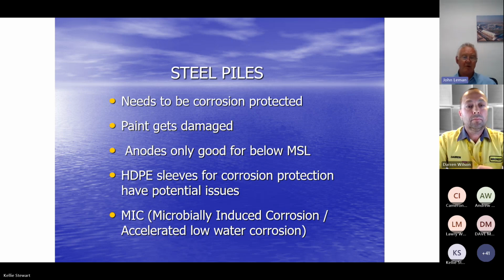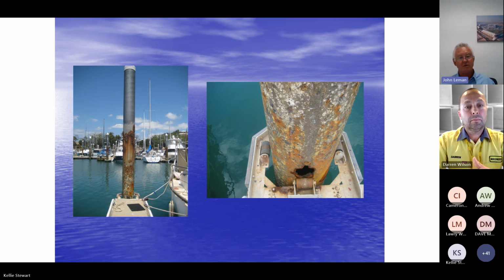The other thing that's become more prevalent is microbially induced corrosion or accelerated low water corrosion. This was actually first found in the States in sprinkler systems in buildings, where they had a sprinkler system that started to get little wet spots or leaks in it, and they couldn't understand why. It was actually an anaerobic microbe that was causing the problem. It's in our marine environment, probably more prevalent in nutrient-rich seabed materials and harbours, and of course being low water corrosion, quite often it's sight unseen, but it's becoming more of an issue.